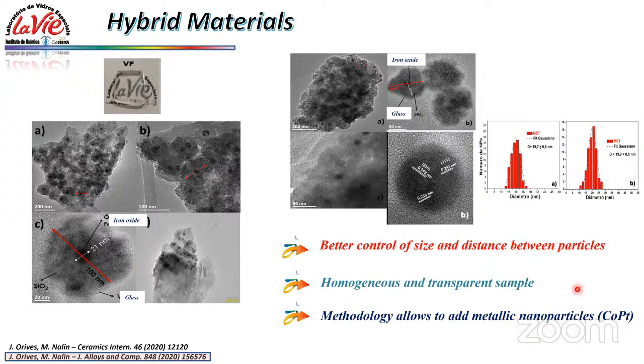We got a homogeneous and transparent sample, and one interesting thing here is this methodology allows us to add, for example, metallic nanoparticles such as cobalt platinum inside this glass. Otherwise, it was almost impossible to add metallic nanoparticles inside the oxide glass. We have no other reference concerning this kind of synthesis. We did that. We published this paper with cobalt platinum later.